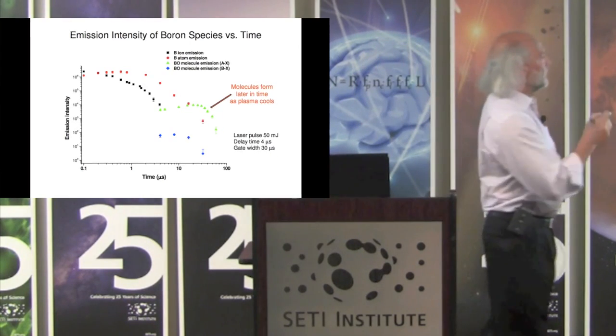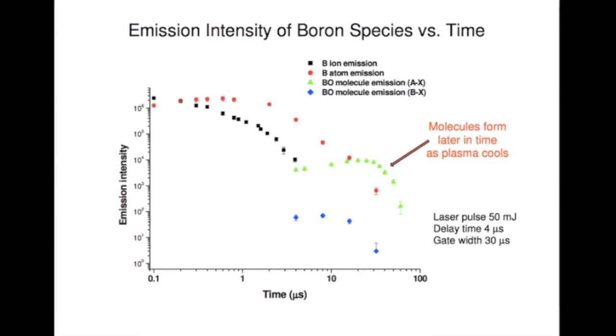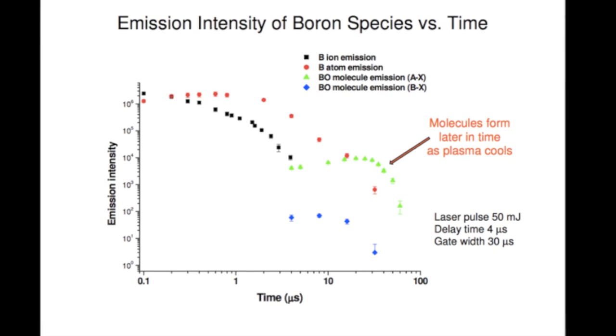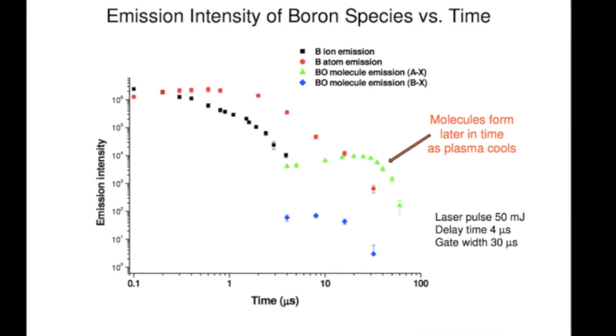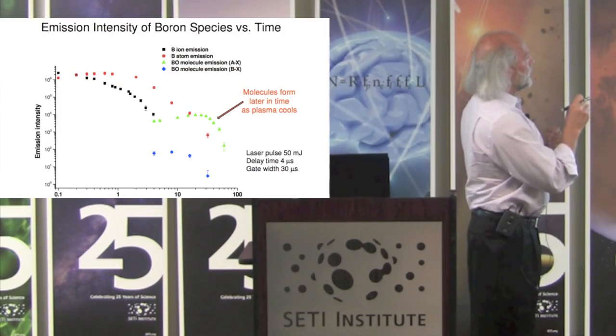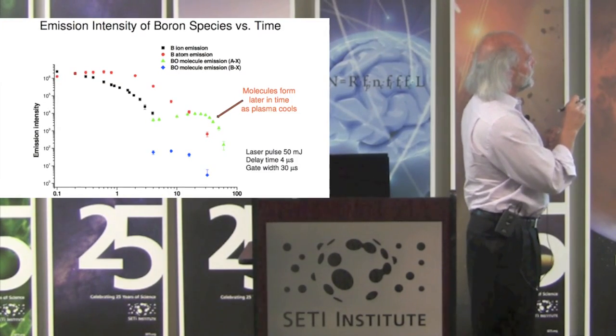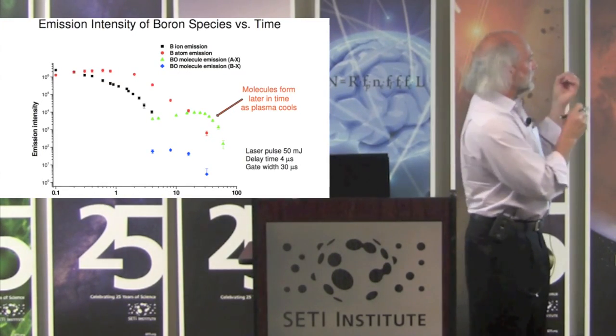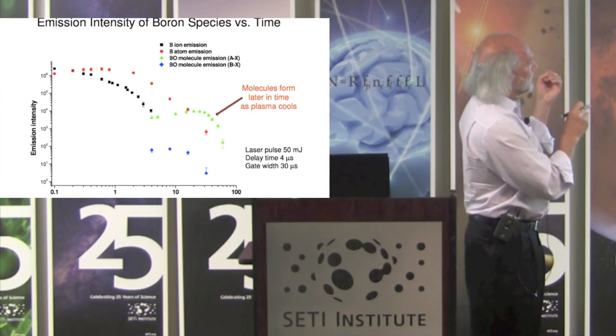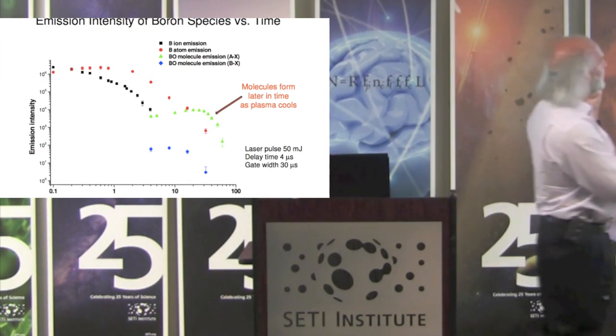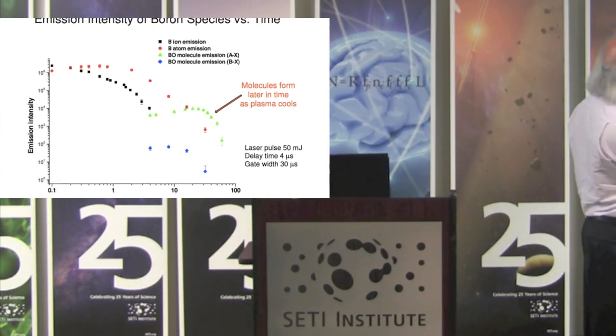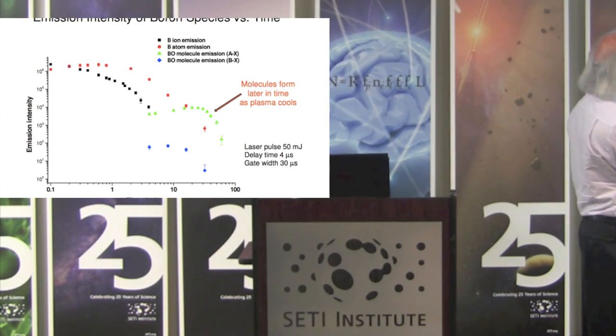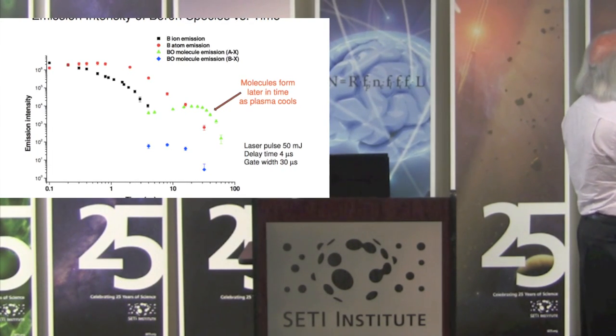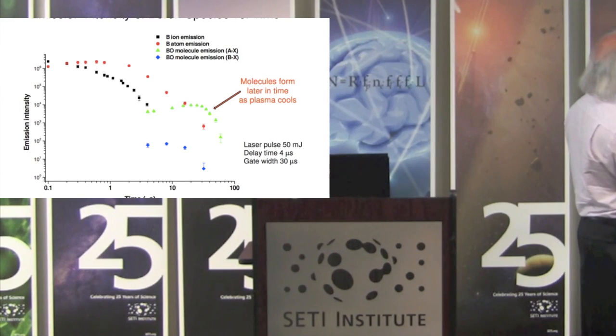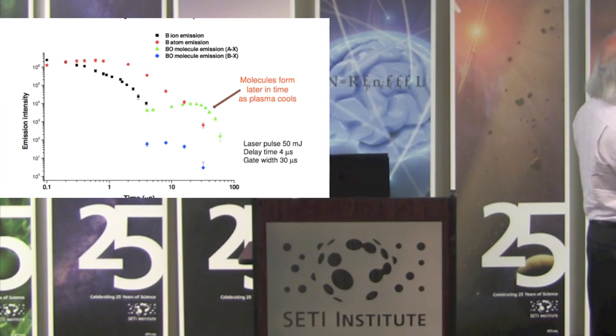So again, a little bit back to the fundamentals of the LIBS plasma. This is when the laser hits versus time as that plasma expands and cools. There'll be boron emission from the ions, which we know the ions emit immediately after the laser pulse. The atoms last a little bit longer. That should be the red. The ion intensity drops off sooner because of collisions. The atomic transitions will last a little bit longer, and this is only on a microsecond time scale.